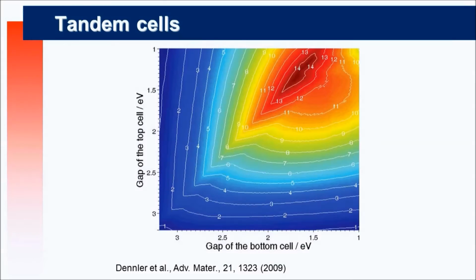If you make a two-layer system where you have one system absorbing one part of the solar emission and another one absorbing the rest, let's say in the near infrared, and you make it in series, you will add the photovoltages, and you may expect efficiency up to 14 to 15%. And Yuning left, but I told him that with Alan Heeger, we got the right combination, and we expect to publish soon an efficiency of about 14-15% when you match everything with the right combination of polymers. I would say it's feasible.